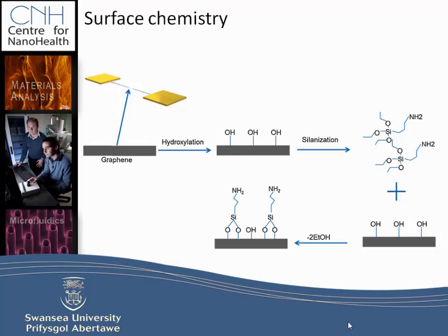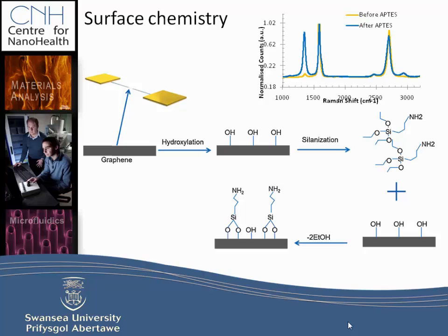Again, a variety of different chemistries. This one we saw similar chemistry in the first talk, but we also use diazonium-based chemistry as well. This is a graphene channel, and what you can see here is the channel before functionalization, which is in the yellow, and then after functionalization, what you're seeing here is the Raman spectrum, and this is the D peak of the Raman spectrum, which indicates increased defect states after functionalization of that graphene channel.